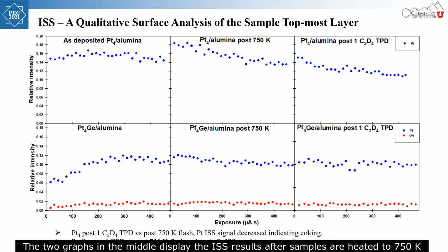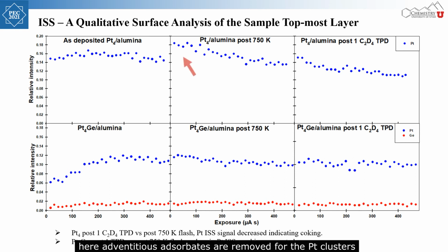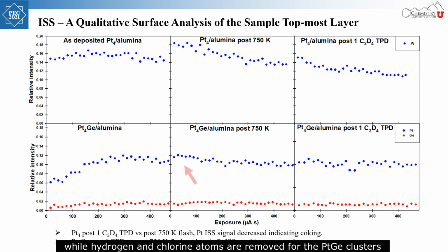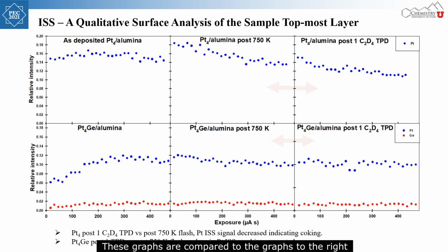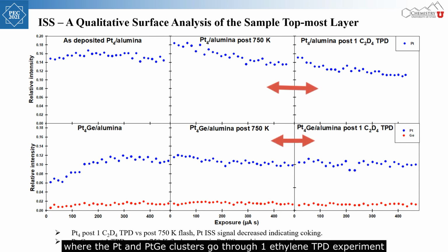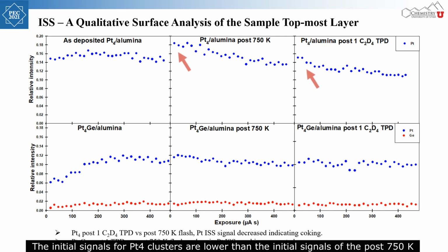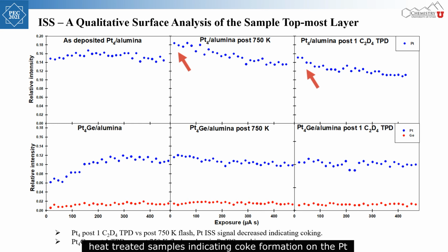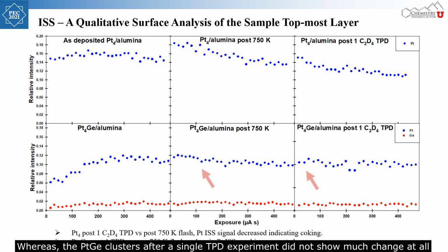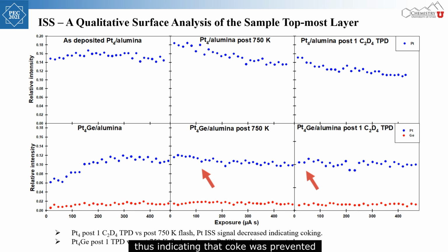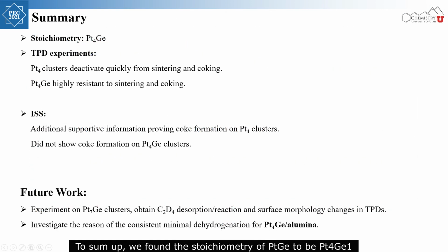The 2 graphs in the middle display the ISS results after samples are heated to 750 Kelvin. Here, adventitious adsorbates are removed for the platinum clusters, while hydrogen and chlorine atoms are removed for the platinum-germanium clusters. These graphs are compared to the graphs to the right, where the platinum and platinum-germanium clusters go through one ethylene TPD experiment. The initial signals for platinum-4 clusters are lower than the initial signals of the post-750 Kelvin heat-treated samples, indicating coke formation on the platinum. Whereas the platinum-germanium clusters, after a single TPD experiment, did not show much change at all, thus indicating that coke was prevented. To sum up, we found the stoichiometry of platinum-germanium clusters to be platinum-4 germanium-1.